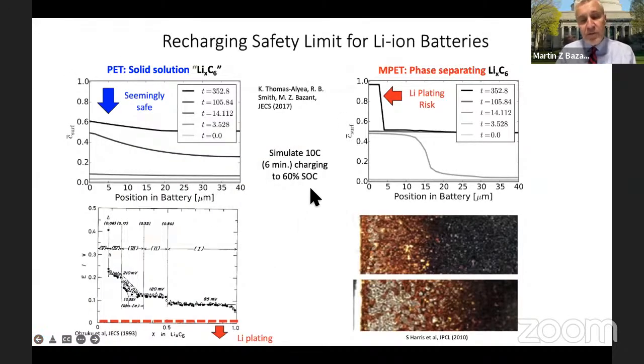And it comes down to all this physics that I'm trying to teach you here, and that we also are learning from images, which is that if you only have a model with diffusion and reaction, there's no way to explain it. Diffusion, transport, and reaction in these graphite electrodes are fast enough to sustain really high currents. You could charge in 1 minute, no problem. The thing is, if you do that, what the correct model gives you is that you will start to trigger side reactions that will rapidly degrade the cell and in some cases even cause safety risk.